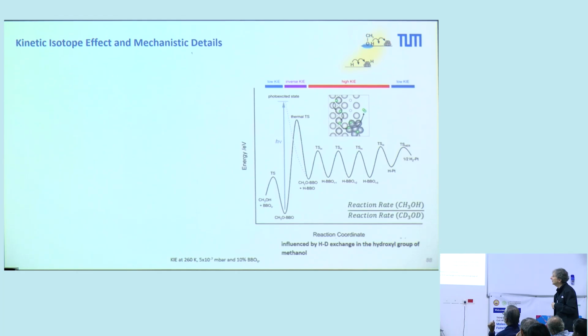Of course, we can try to quantify this. And for this, we can use the kinetic isotope effect. It is the reaction rate of methanol divided by the reaction rate of your other species. And if you look now at our mechanism, you have first the adsorption of your alcohol and the formation of the methoxy. This kinetic effect has been measured. It is about 1.3.